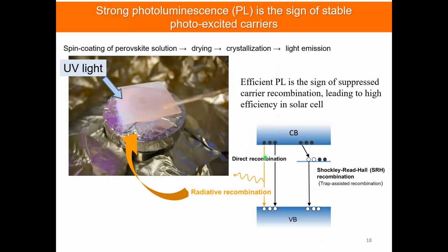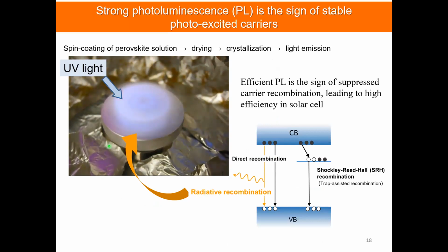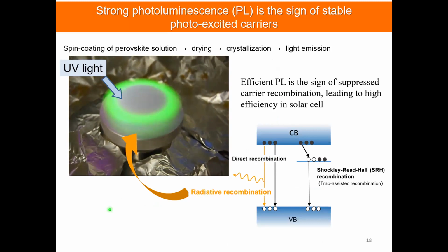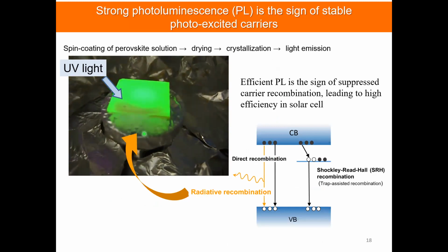This video now shows the perovskite solution being coated on the substrate, and this spin coating machine is making a thin layer of liquid. Simultaneously, the solvent is evaporated within almost 1 minute. So you can see a very brilliant green emission from this crystalline layer. That indicates the crystalline layer was formed on the substrate in a very, very short time.